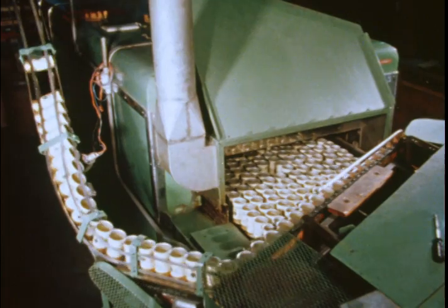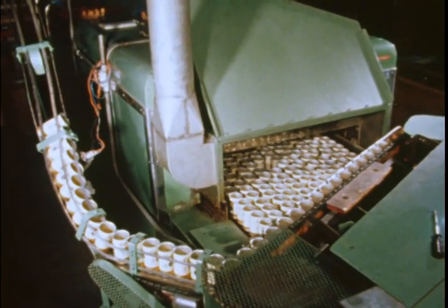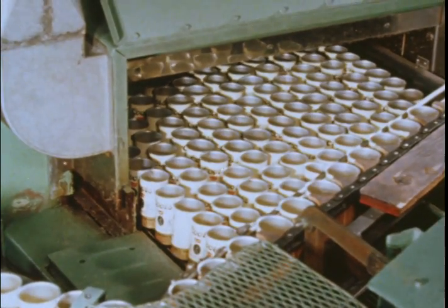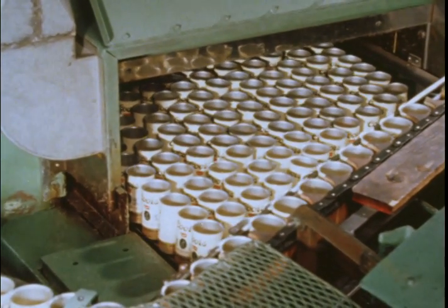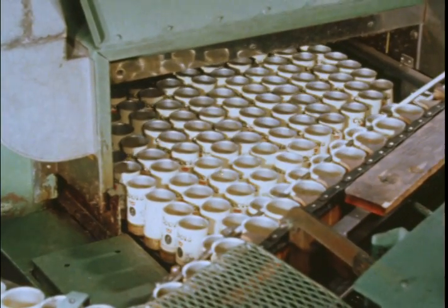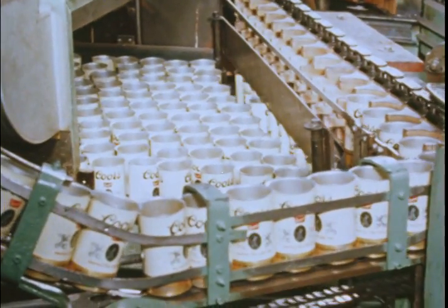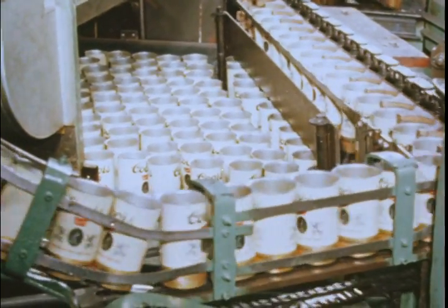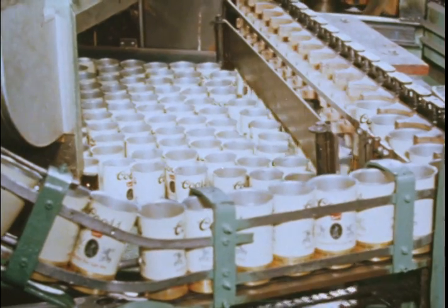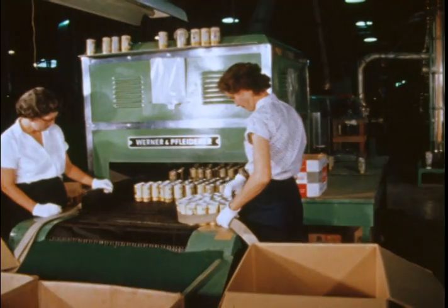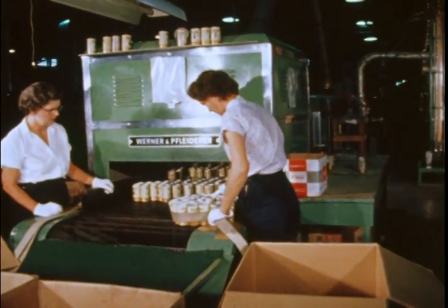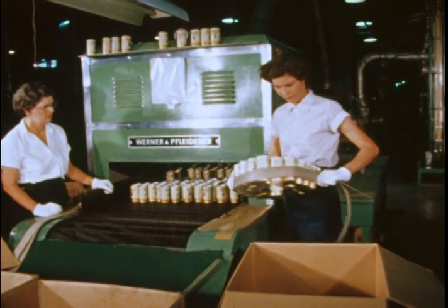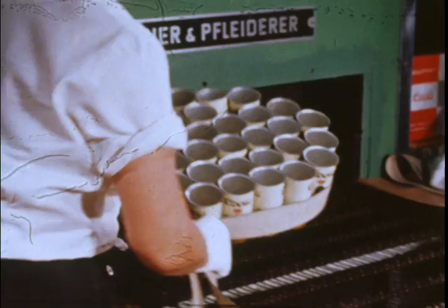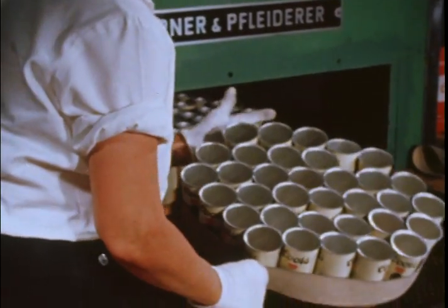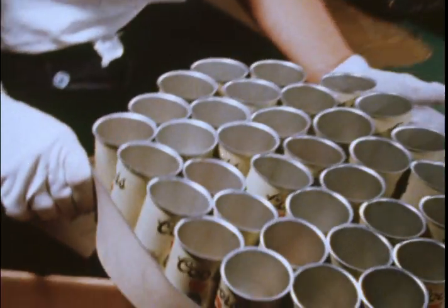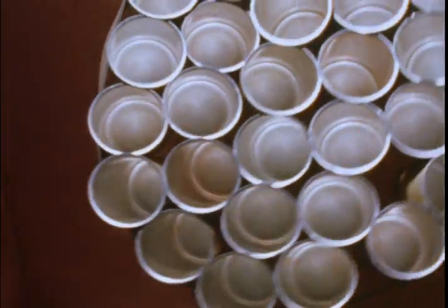The final operation is this baking oven. The cans receive a 10-minute bake at 400 degrees to thoroughly set the internal vinyl lining and the external inks. Inspection is next, with the finished cans being dumped helter-skelter into reshipping cartons for transport to the brewery.